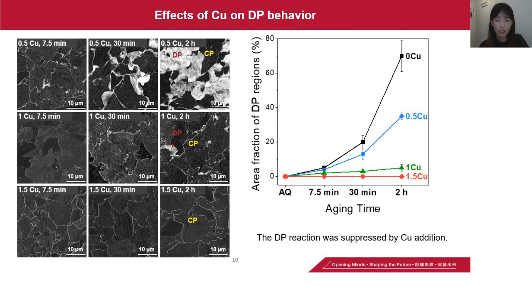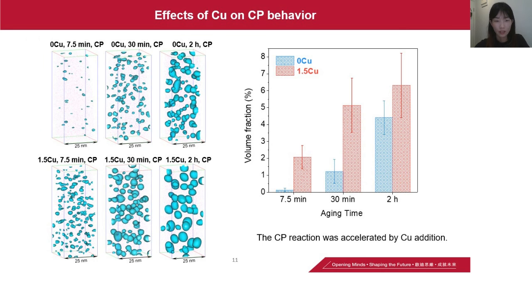Because only CP was found in the 1.5 copper steel, we now compare the continuous precipitation in 0 copper and 1.5 copper steel. The atom probe tomography was performed in the CP regions of the 0 copper and 1.5 copper steels in the three aging conditions.